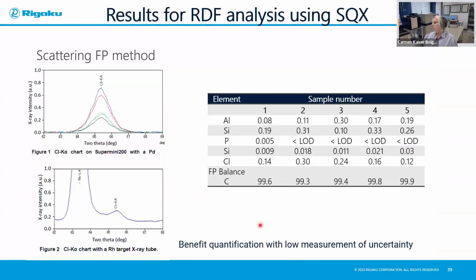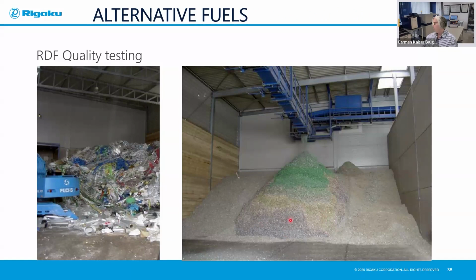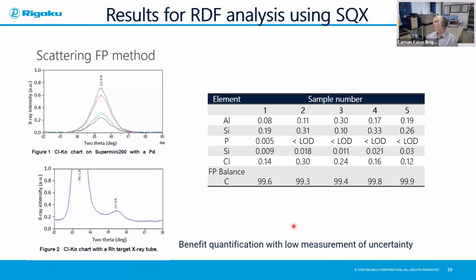So, of course, from this pile, we took 5 different large samples, because it's a big stockpile. And the large samples were treated in the same way as I described before, and we prepared the sample 5 times. And of course, as you can see, it's a very heterogeneous sample. Using the scattering FP, once again, to estimate the balance of the material, we have defined the balance here. So the more consistent the definition of the balance, the more consistent the analysis of your results will be here.